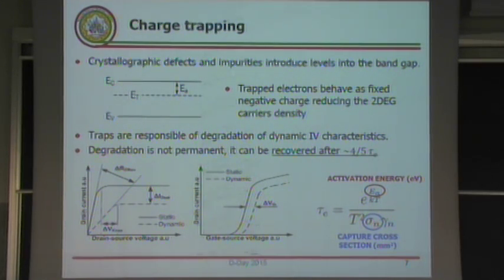However, these degradations are not persistent, but are recovered after some time in a low voltage state condition. But the time required for the recovery of the device characteristics depends on the characteristic emission time, tau E, which depends on trap properties like activation energy and capture cross-section, and is also dependent on the temperature of the device.